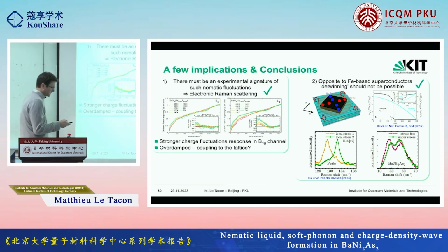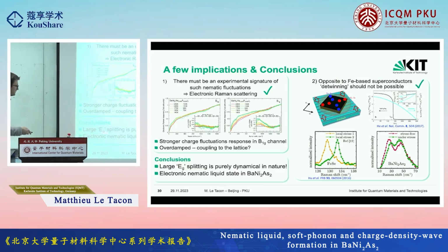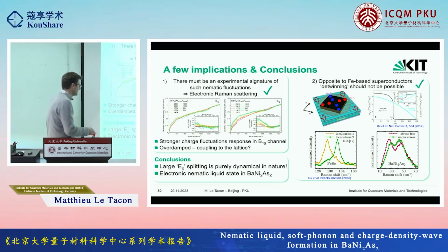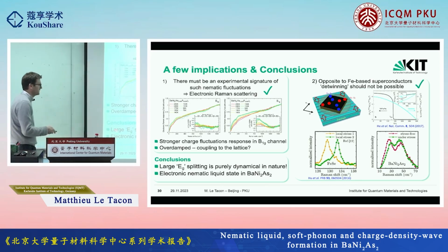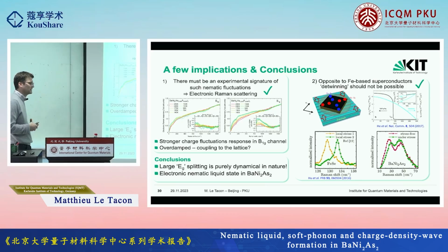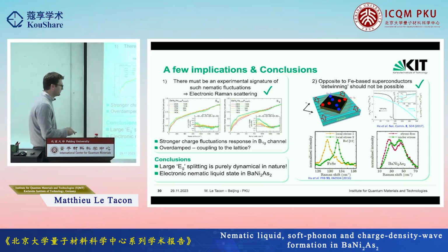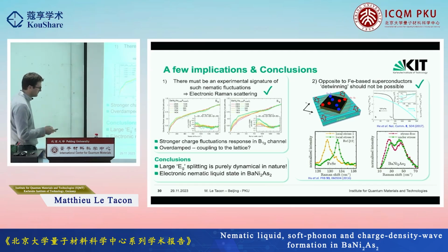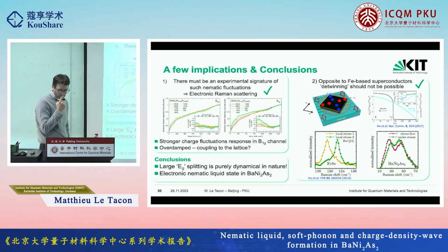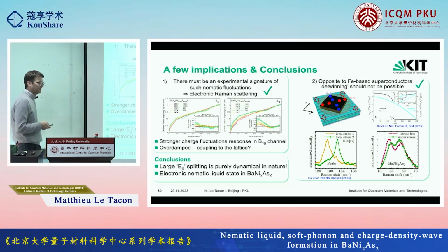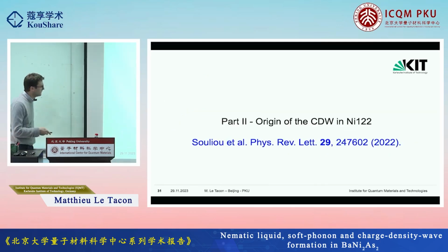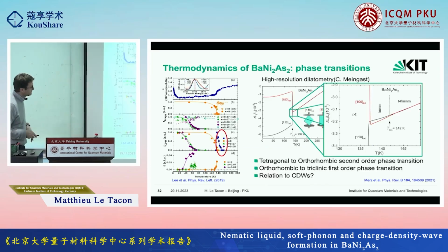So with this, we were quite happy, and basically what we concluded from that is that this large EG splitting, despite being so large, is the signature of a purely dynamical effect that we call the electronic nematic liquid state in the BaNi2As2. So I've not been doing so bad so far, and I can just switch to the last part of the talk, which is the origin of the charge density wave.